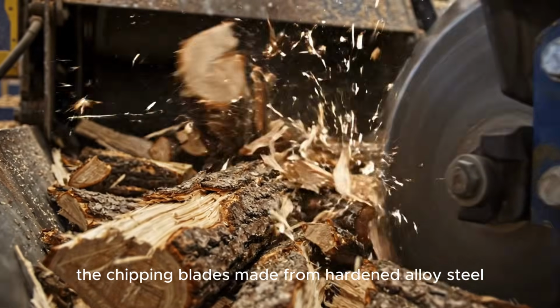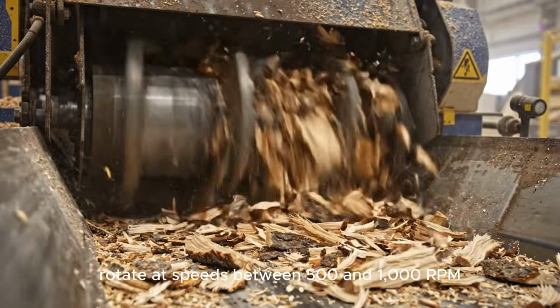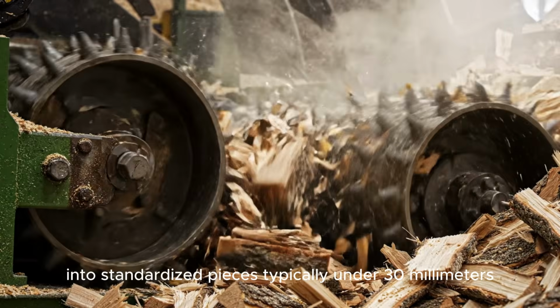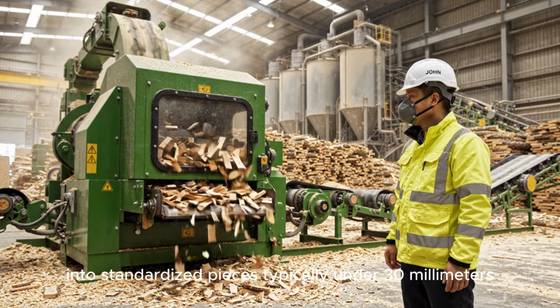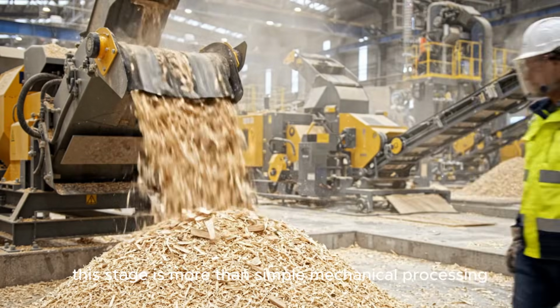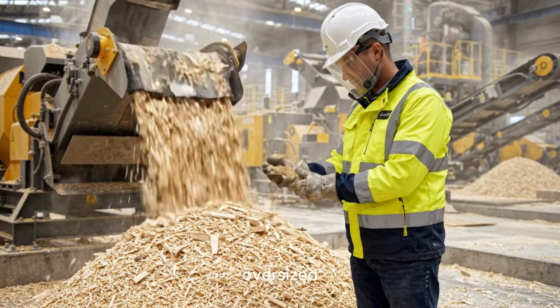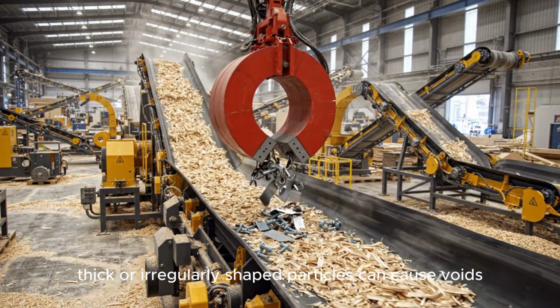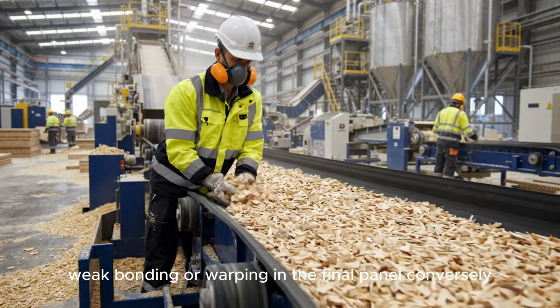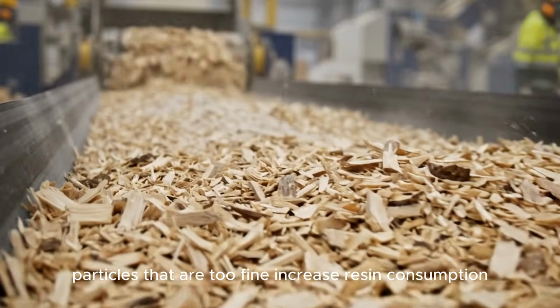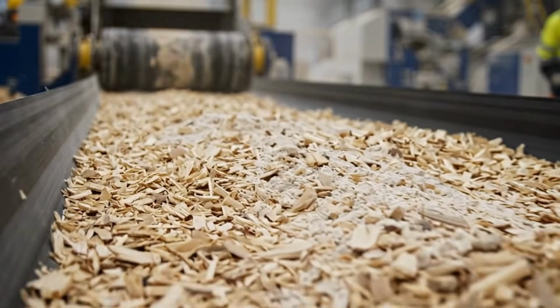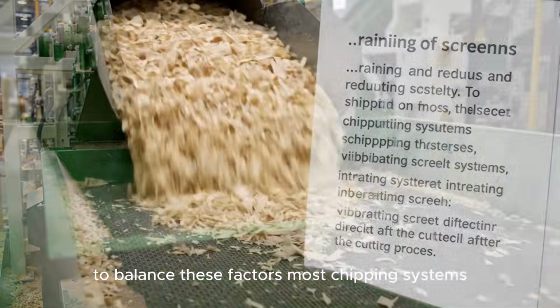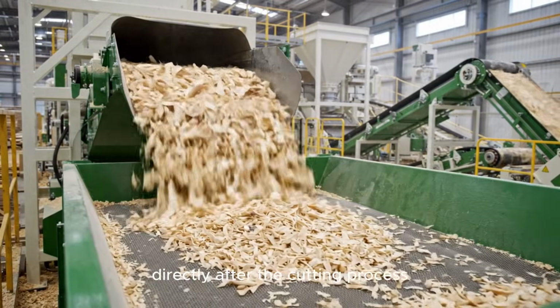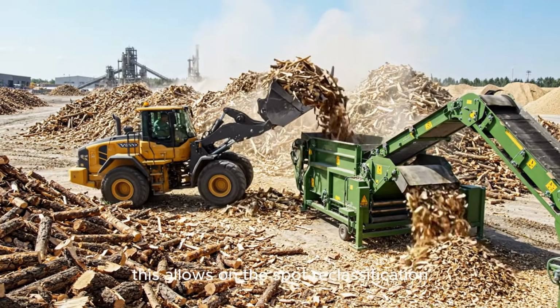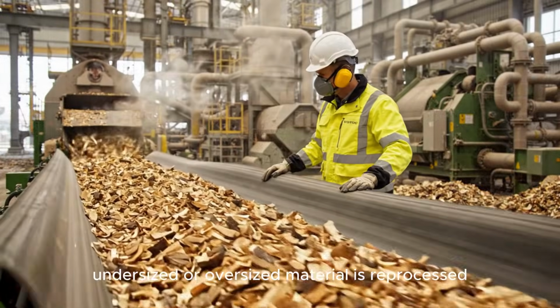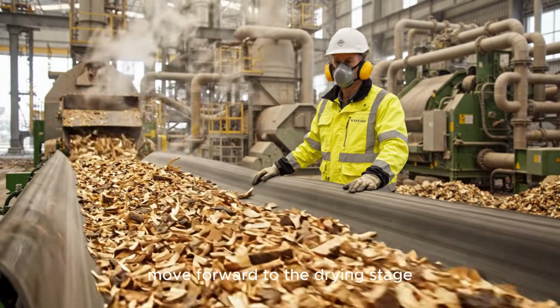The chipping blades, made from hardened alloy steel, rotate at speeds between 500 and 1,000 RPM, continuously cutting the material into standardized pieces, typically under 30 millimeters for conventional particle board. This stage is more than simple mechanical processing. Oversized, thick, or irregularly shaped particles can cause voids, weak bonding, or warping in the final panel. Conversely, particles that are too fine increase resin consumption, raising costs and reducing stability. To balance these factors, most chipping systems integrate vibrating screens directly after the cutting process. This allows on-the-spot reclassification. Undersized or oversized material is reprocessed, while properly sized particles move forward to the drying stage.